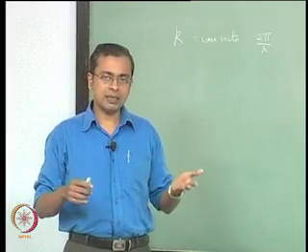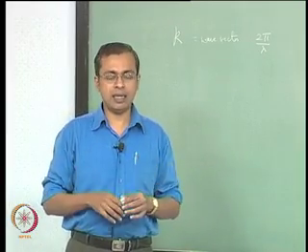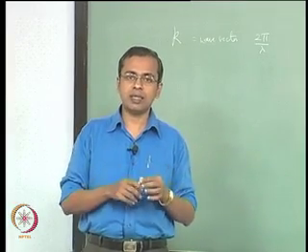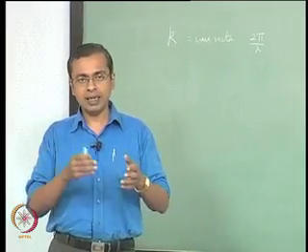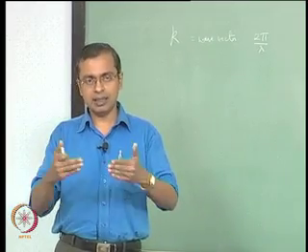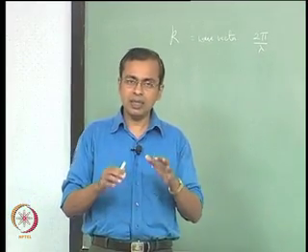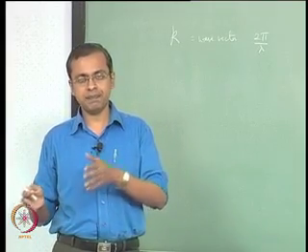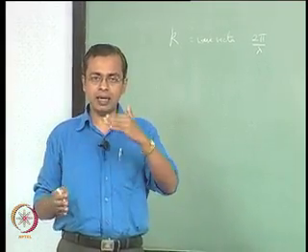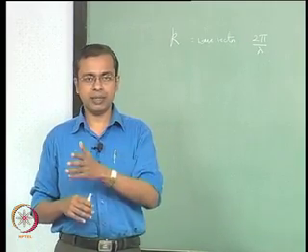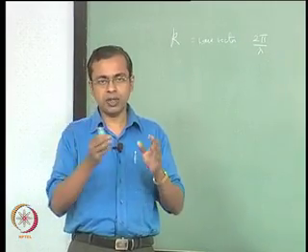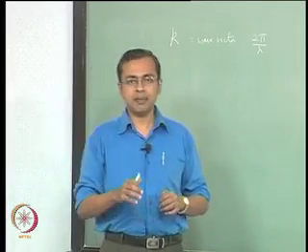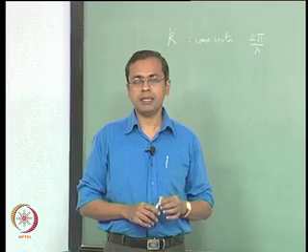Of course, last class we looked at the reciprocal lattice as an independent entity. We just basically said that, given a real lattice which has unit vectors a1, a2 and a3, we can specifically create a reciprocal lattice which corresponds to this real lattice, with the definition of the reciprocal lattice vectors, unit vectors in the reciprocal space b1, b2 and b3, having specific relationships to a1, a2 and a3. Okay, so we had a cross product: b1 was a2 cross a3 by the volume of that unit cell, and similarly b2 and b3 were described.